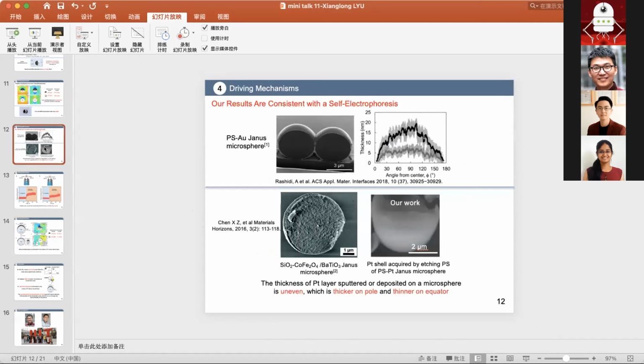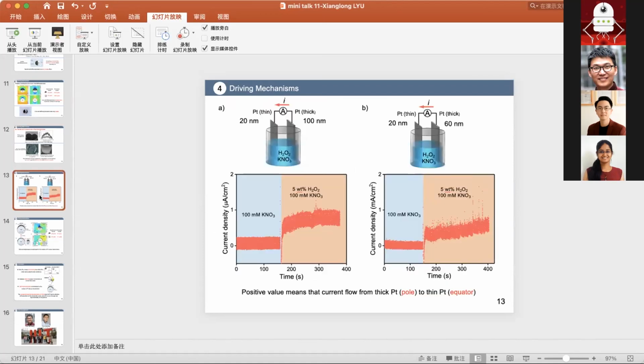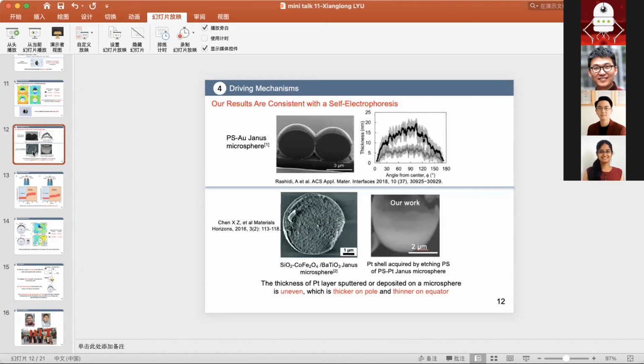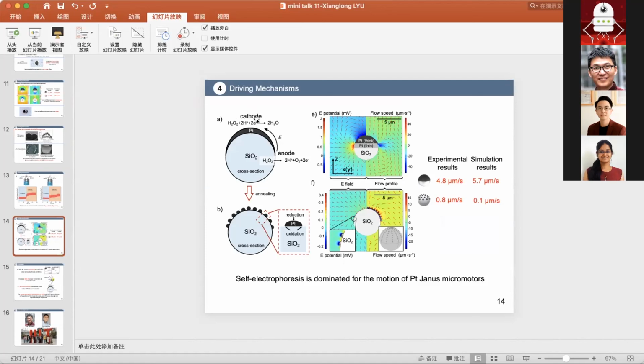Oh, okay. We prepared the Janus microsphere by sputtering vertically. So on the pole, the thickness of the platinum is thicker, and on the equator, the thickness of the platinum is thinner. And according to the literature, the thicker the platinum film, the higher their catalytic performance. So according to our results of electrochemical measurements, we confirmed that the thick platinum film served as a cathode, and the thinner platinum served as an anode.